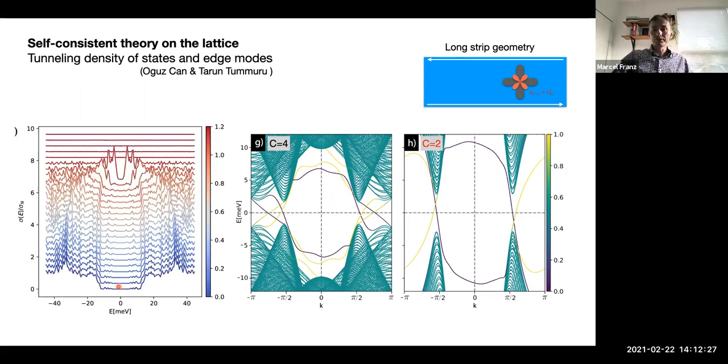It's much larger in the Chern number equals 2 phase, presumably because the Fermi surface is then simpler and the gap is not as much frustrated due to the presence of two complicated Fermi surfaces. And in this situation, the gap can be quite large, 15 meV or so, and it should be very easily observable by spectroscopies.